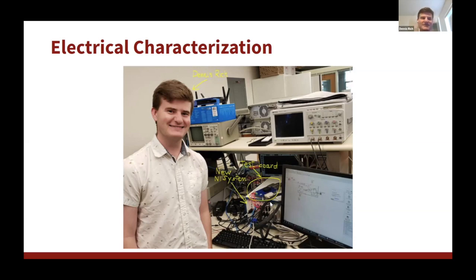These changes are made by heat, the phase changes, and you actually have to get up to about 600 Celsius to change the phase in memory, which sounds insane, but it can be done in computers, and it has been done in computers because it's lightning fast. You can get up there super quickly, and then you go right back down. If you're heating up a small enough area, the amounts of energy required aren't that high, and they don't spread. So this has been shown in full-scale computing systems.